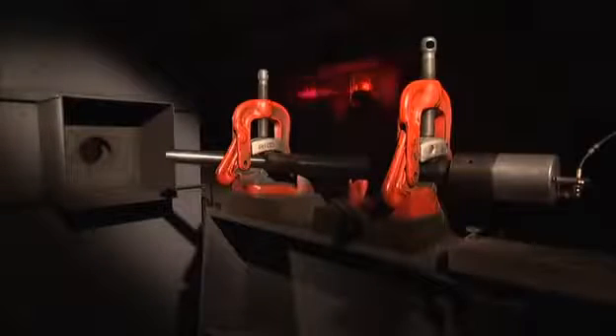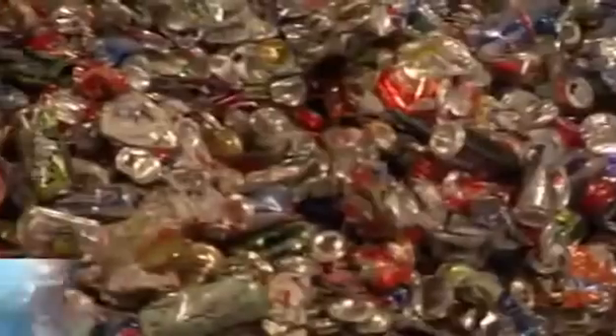Finally, the panel is ready to be tested against a deadly round on the battlefield, the .50 caliber. On the back side here, you can see that there's a bulge, but there's no hole, and that this did prevent the bullet from penetrating it. Not only did this aluminum panel stop the round, but this material is lighter, thinner, and tougher than a similar sheet of bulletproof glass. I know it'll be saving a lot of lives. A lot of soldiers' lives. They put their lives on the line for us, and these materials will help them out a lot.